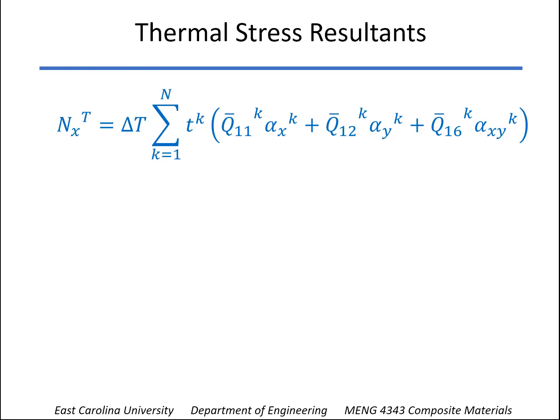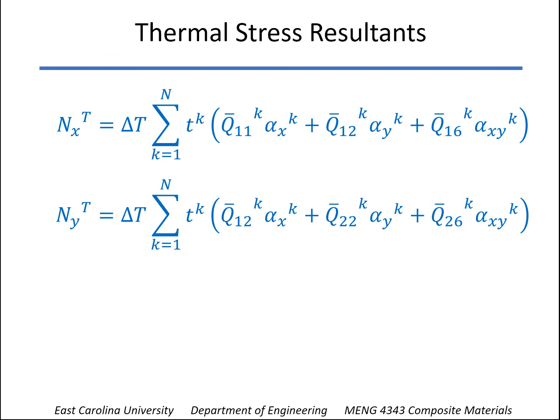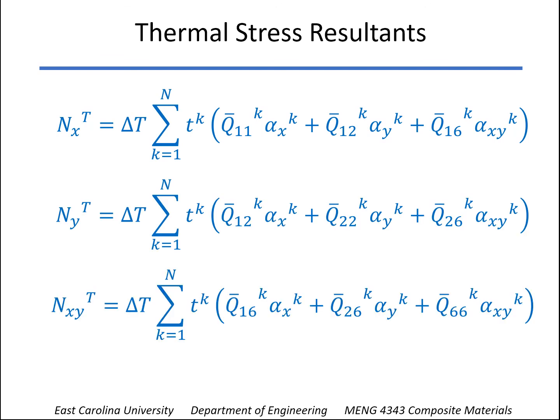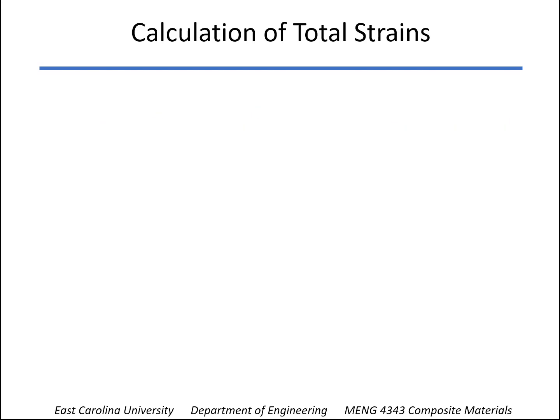And so we can write those out like this. If we take the first row of the Q bar matrix, multiply by the thermal coefficients, multiply that by the thickness for all the layers, sum those up for all the layers, multiply by delta T, then we have Nxt. Similarly for Nyt and for Nxyt. The only difference is now for Nyt we're using the second row of the Q bar matrix, and for Nxyt we're using the bottom row of the Q bar matrix. So those are the thermal stress resultants.